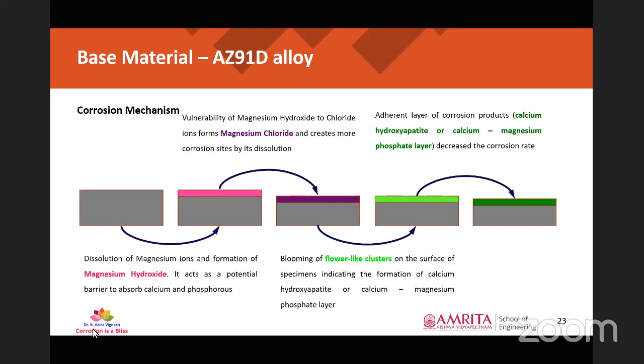Once we immerse magnesium alloy into the body, there will be formation of a magnesium oxide layer. Then because of an aqueous environment, magnesium hydroxide forms. Magnesium hydroxide is very active, so it reacts with chloride to form magnesium chloride. This magnesium chloride goes into solution because of its high solubility. Then because of the high accessibility of magnesium to phosphate and calcium elements present in the human body or this Dulbecco's phosphate buffered solution, it is going to form calcium hydroxyapatite crystals or calcium magnesium phosphate based crystals. So this will enhance the osteoconductivity also.